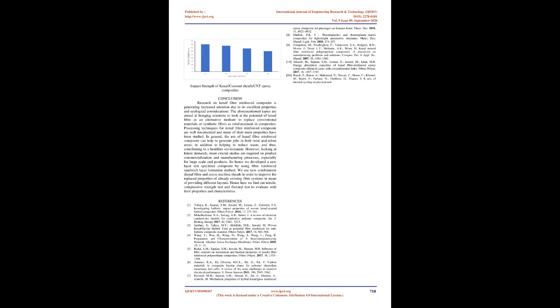The results from the Izod impact test of hybrid Kenaf/Cocos Nucifera Sheath reinforced CNT polymer composites are shown in Fig 9. The impact toughness of the L1 laminates possess the highest impact toughness among the laminates. Addition of Cocos Nucifera Sheath with the Kenaf fabric reinforced epoxy composites declined the impact toughness only by 4.4%. Both L3 and L4 laminates showed almost similar impact toughness.